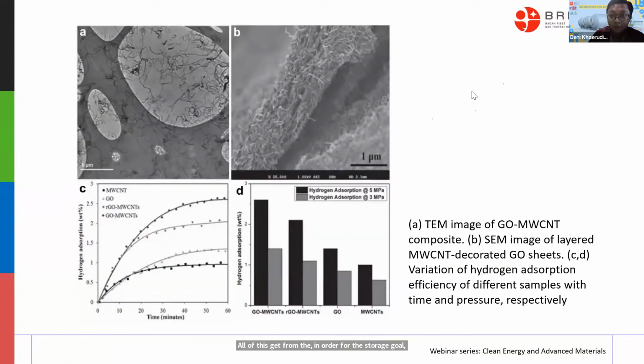Okay, maybe you are also curious what kind of morphology the carbon sorbent material has. So this is the multi-wall carbon nanotube, graphene oxide, and also GO and RGO combined with the multi-wall carbon nanotube. So the performance is quite different. Again, this also has a hydrogen uptake, or absorption, of about 3, but this one is less than 3 compared with the previous research. So this is the kind of morphology that we need to achieve. The pore size is usually less than 100 nanometers, like 20 or 30. Maybe I will show you later on.